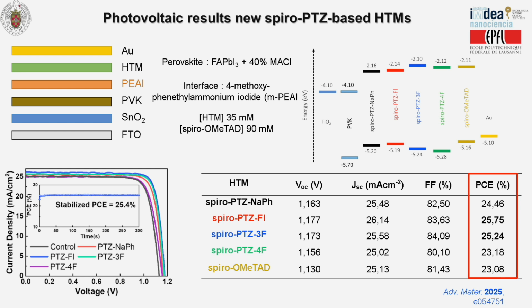When we got this result, the maximum was 25.8. At that time, the world record was 26.2. So we were very close to it. However, it took us almost 1 year just to get all the results, repeat many things, and eventually the record was increased a little bit more. But these are fantastic behaviors for these systems.